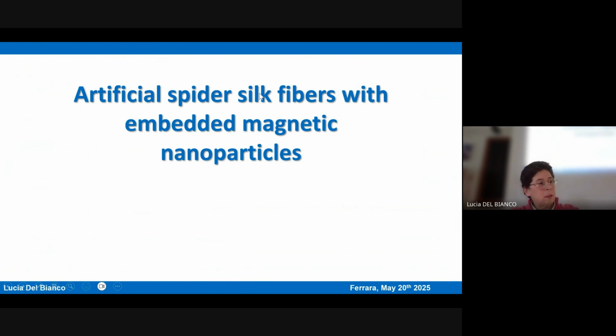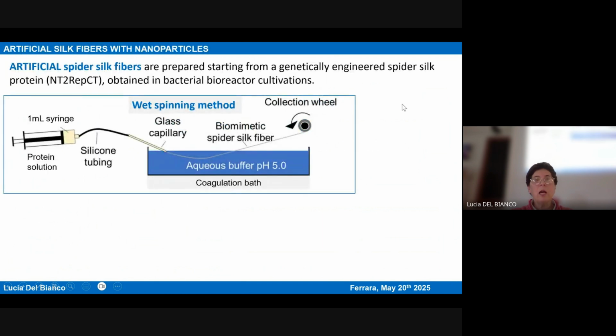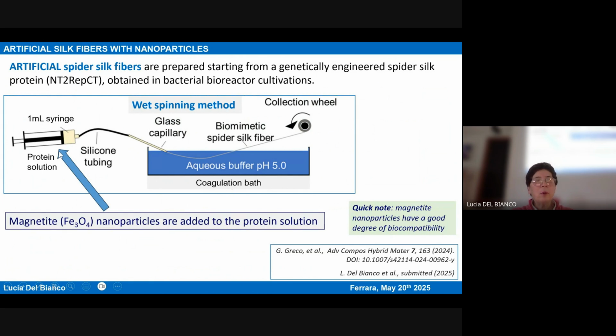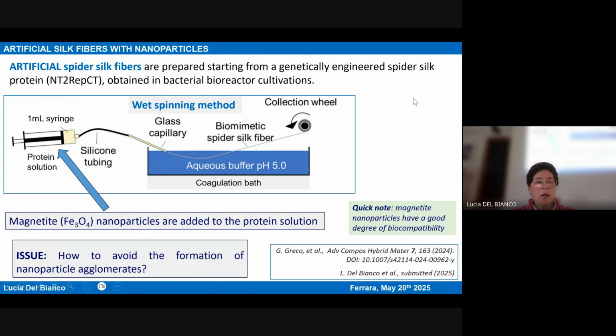So, at last, we can speak of the first class of samples that we have prepared. So, artificial spider silk fibers with magnetic nanoparticles embedded. How to do that? Well, you remember how the artificial spider silk fibers are produced by our colleague in Sweden, and therefore the idea was apparently simple. Okay, let's add some magnetite nanoparticles to the protein solution, and so we will obtain a fiber with embedded magnetic nanoparticles. But things are not so simple because nanoparticles tend to form agglomerates.